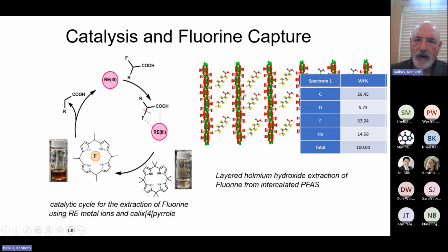And here's an example of a rare earth double hydroxide. So the metal hydroxide itself is cationic. Normally, these layered clay-like materials are anionic, but for these double hydroxide type structures, they're cationic, and so they very effectively adsorb the PFAS. And you can actually see, if you just look at the EDAX of these double hydroxides with the fluorine, that they readily adsorb the PFAS. And of course, you can see the layer expansion in these structures. And so this might be a way in which you can combine the adsorption and then ultimately the conversion of the PFAS as well. So those are some of the things that we're also trying to take a look at.